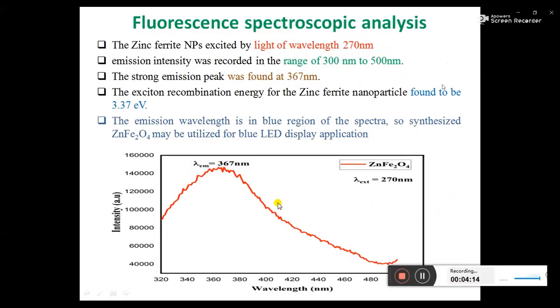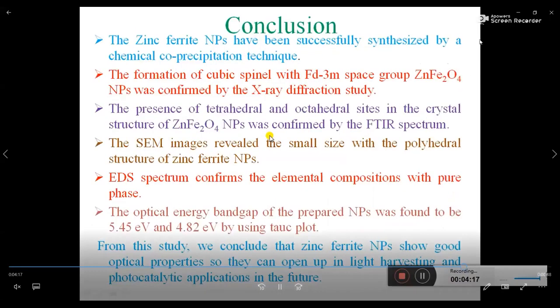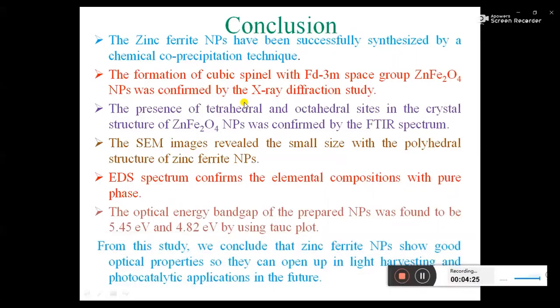Conclusion. From the co-precipitation method, we have successfully synthesized the zinc ferrite nanoparticle and confirmed the cubic spinel by XRD, and the presence of tetrahedral and octahedral sites by FTIR spectrum. And SEM revealed the polyhedral structure of the zinc ferrite nanoparticle. EDS spectrum confirmed the formation of zinc ferrite nanoparticle. And also we have calculated the band gap from UV visible spectrum using Tauc plots.